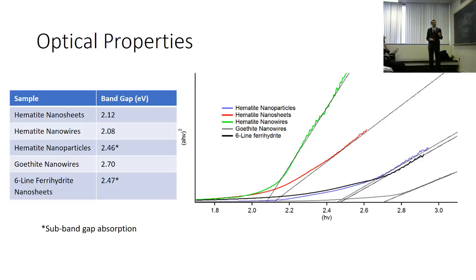First difference in property is band gap. For hematite, band gap doesn't really change depending on structure as much, whereas in copper oxide it's changing all over the place. Hematite's pretty stable, about 2.1 or 2.2 electron volts, and for my nanosheets and nanowires that's about what it is. For the nanoparticles, it was much higher.